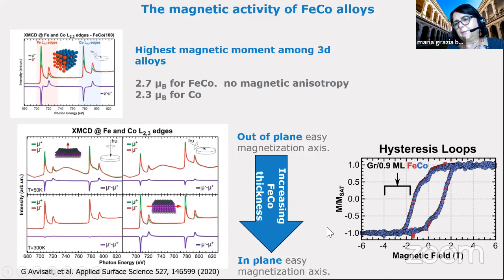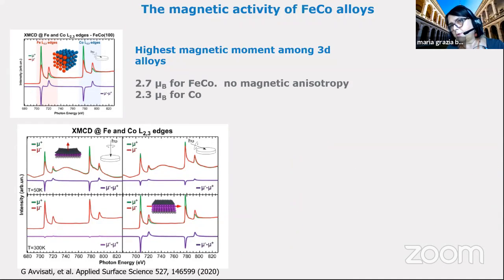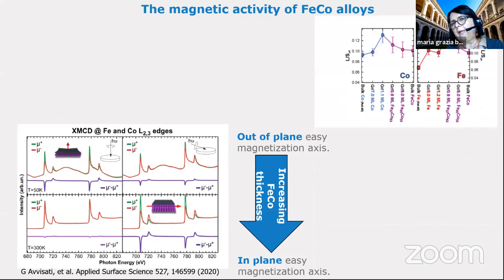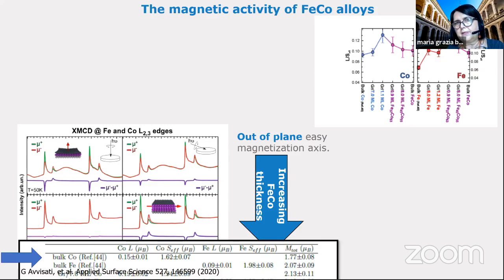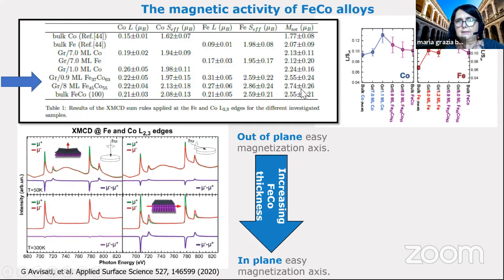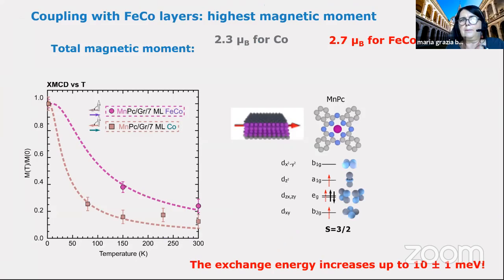Then using the selection rules and the sum rules, we obtained the orbital moment and the spin moment of the system, and then calculating the total magnetization, you can see we have a very important increase of the total magnetization in this system. Then the idea is, let's try to couple the molecule with this other substrate. This is the experiment where, as a function of temperature, I show you the total magnetization normalized with respect to the response when we have only cobalt. So this is with the iron cobalt alloy, and this is only cobalt.